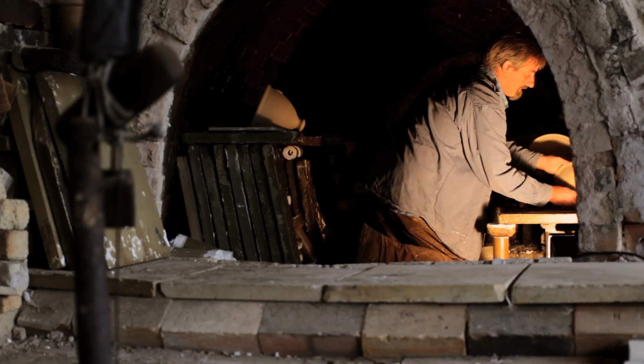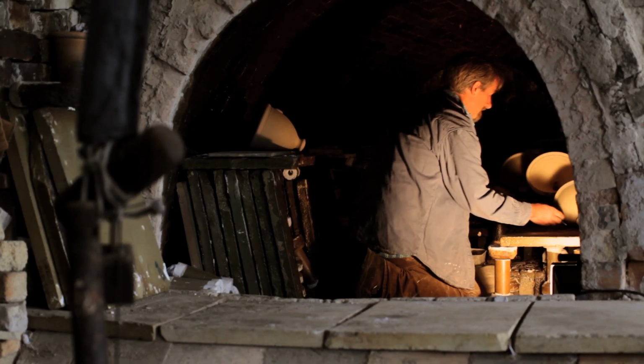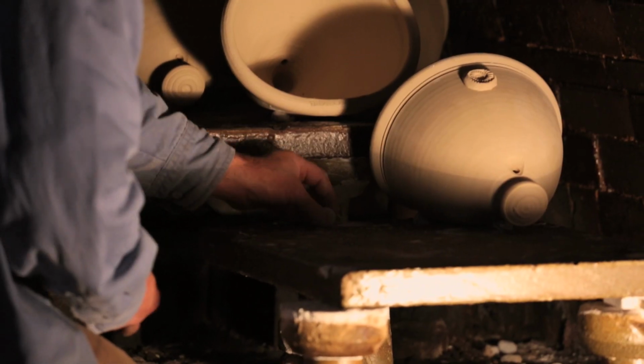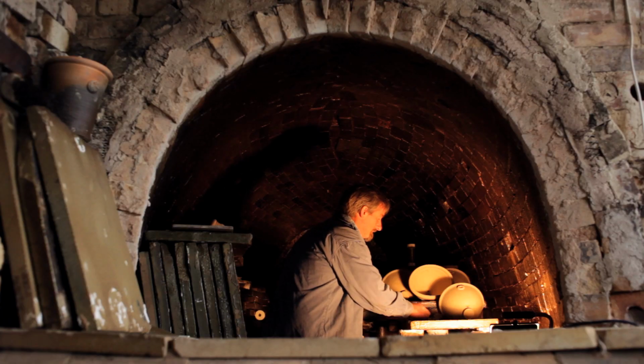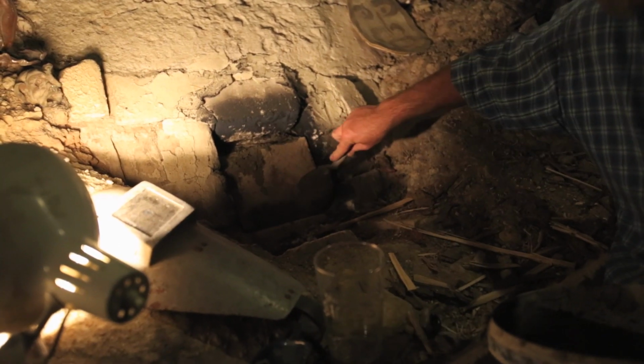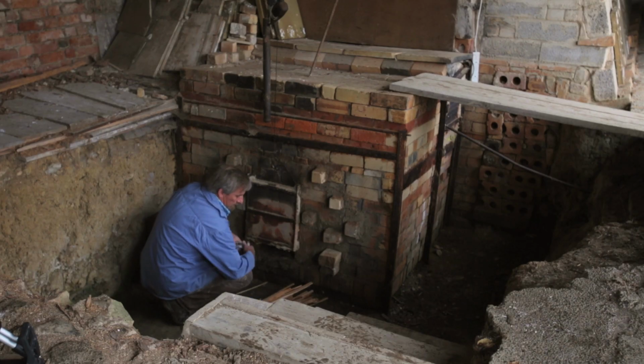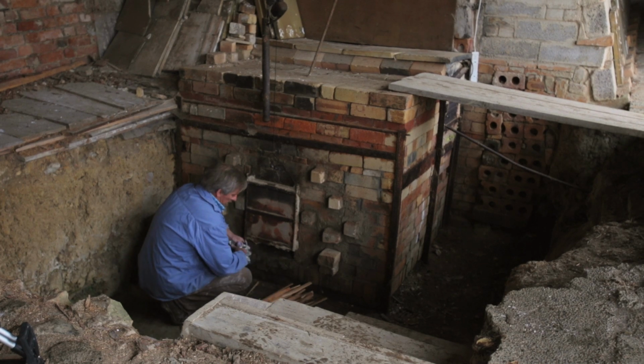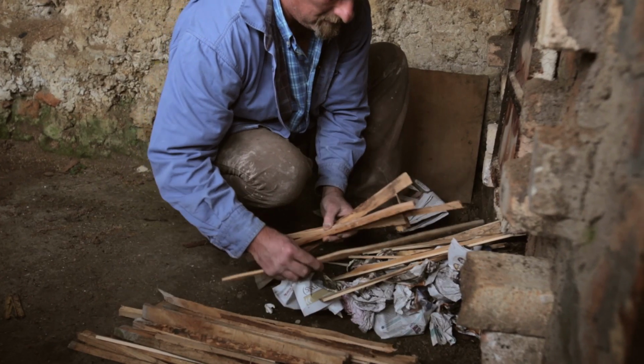It takes me about 3 days to pack all the pots inside the kiln. I guess the chamber is about 170 cubic feet, and gradually over 3 days I fill that space entirely. The doorway, or the wicket as it's known, is bricked up and sealed in, and then basically the kiln's ready to fire. We start a very small fire outside the kiln and gradually introduce it into the firebox.